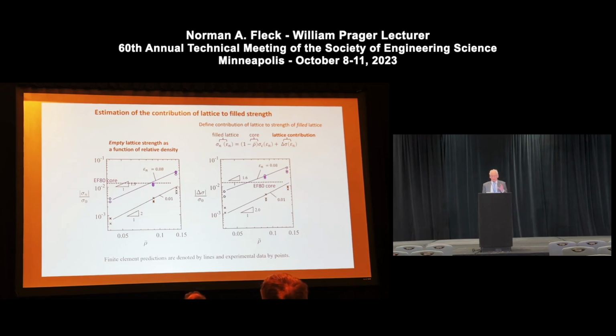Okay. In order to try and probe whether the lattice itself is behaving in a much stronger manner when one puts in the incompressible core, a way to do that is to take the observed stress-strain curve of the filled lattice, subtract off from it the contribution, thinking of this like a Voigt-Reuss bound style rule of mixtures. So subtract off from the stress-strain curve of the filled lattice, the stress-strain curve contribution due to the volume fraction of the core times the stress-strain curve of the core, and you're left with this lattice contribution. So we can use the observed lattice stress-strain curve, the observed core contribution, and deduce how much of the macroscopic response is coming from the lattice.